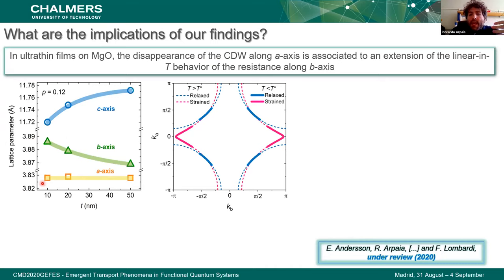So the orthorhombicity increased, and the increase of orthorhombicity is connected to a modification, predicted theoretically, of the Fermi surface that makes the Fermi arc to be closed along the b-axis direction.